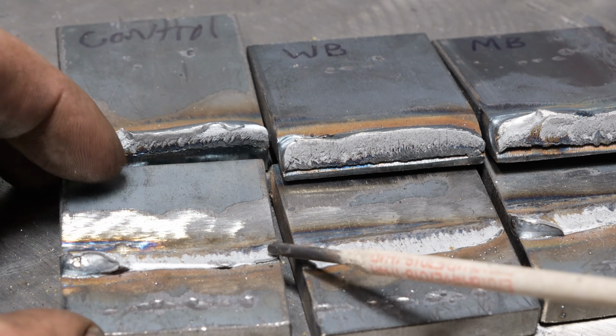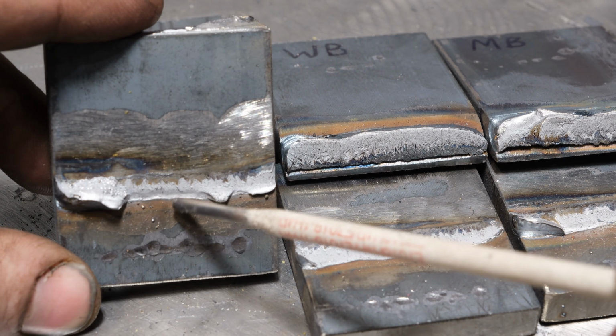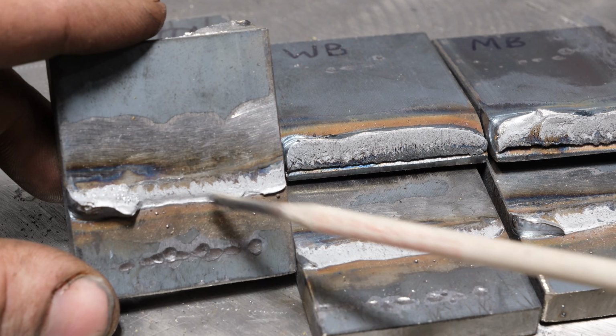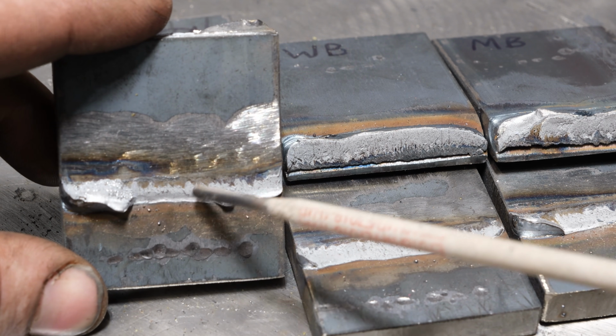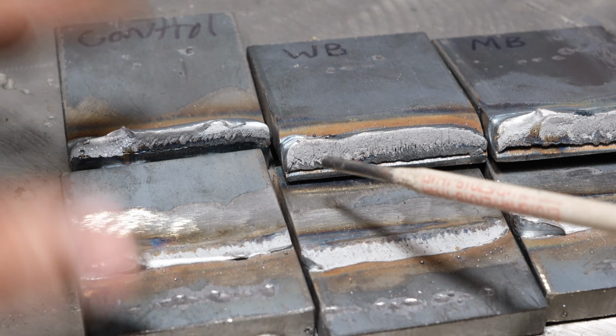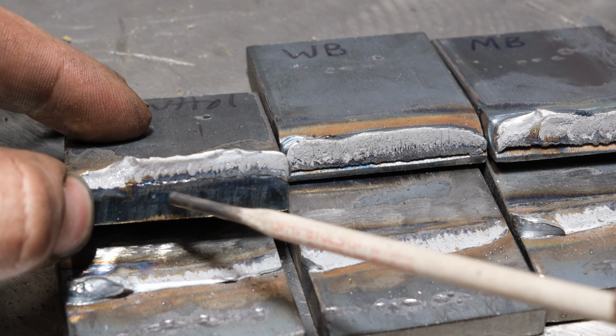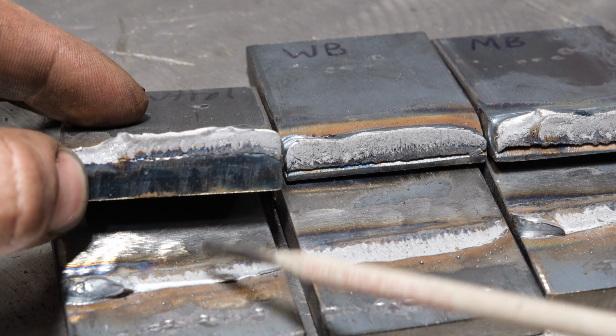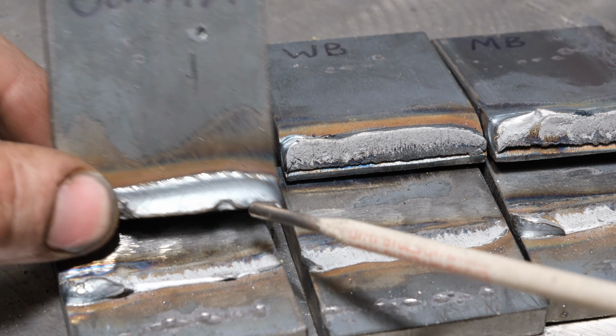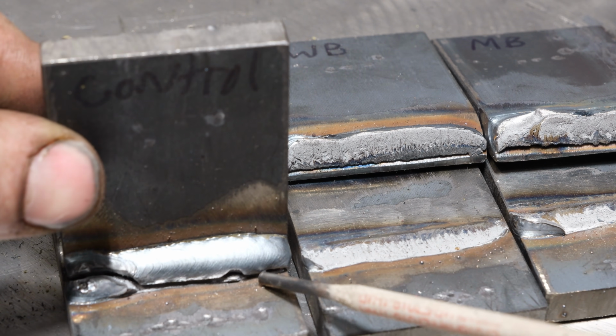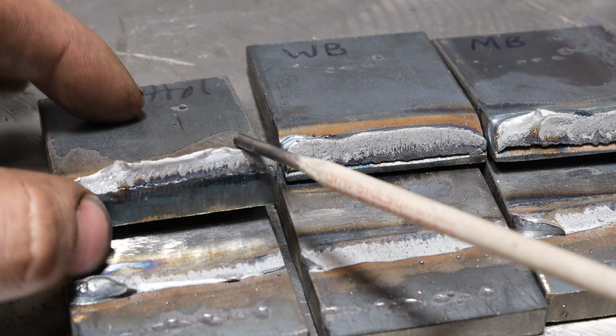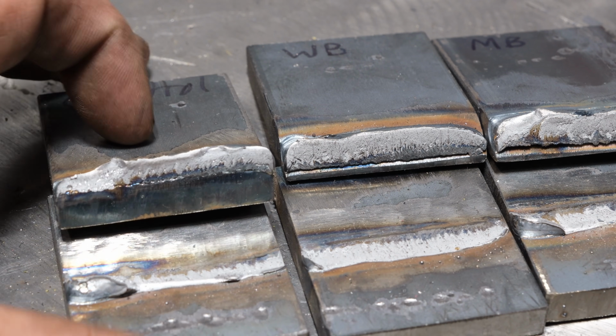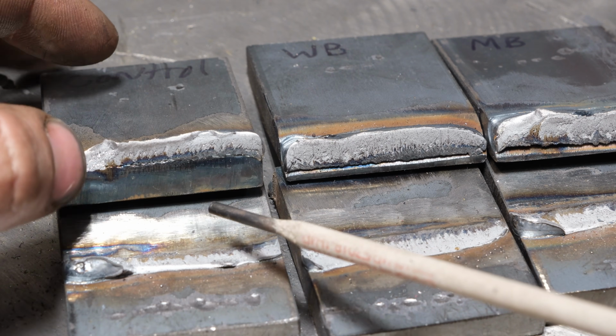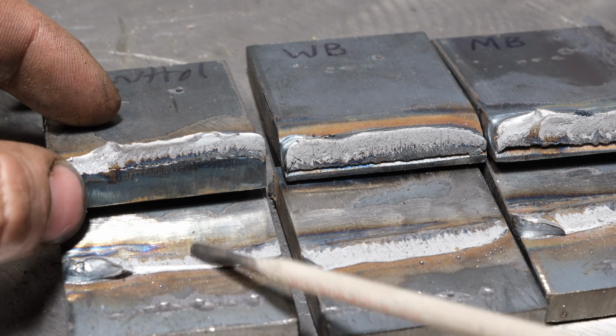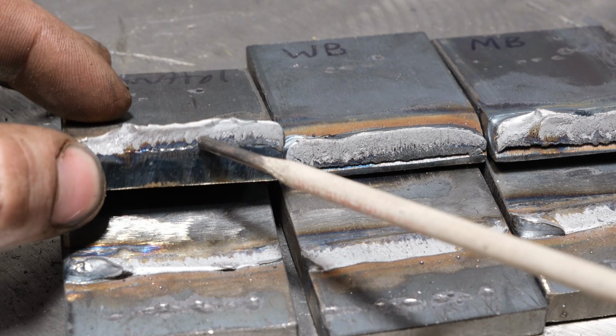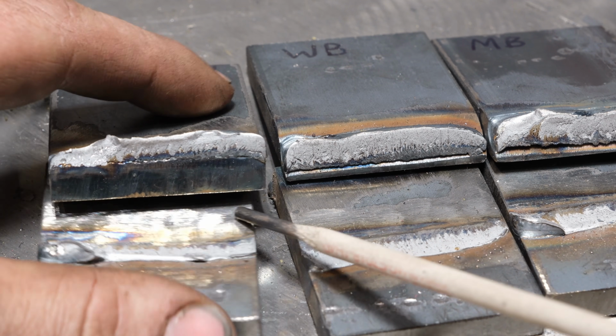Now, the bottom plate is quite interesting because when you look here, there's very little bite into this plate at all. So not only did it tear off here, but the width of the fusion there is very limited. Now this weld goes from about right here to right here, so clearly a lot of it didn't even fuse on there. This weld is actually the smallest out of all of them for the most part, so that's part of the reason why it broke at probably a little bit less than it should have. But let's face it, guys, you're just not going to get much fusion when you run straight in a corner like this with the short circuit process. Spray arc is by far better.